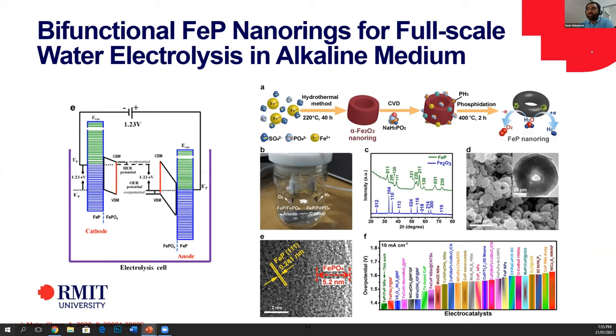So if you look here, we have some surface coating. We have a strain through the ring structure. The ring is hollow inside, so the electrolyte can go easily into the structure. And the strain at the edges or the curve of the ring is very useful to create active sites. When we apply it for the oxygen evolution reaction and hydrogen evolution reaction in alkaline media, it gives us extraordinary performance, and we found that this is among the very best reported in the literature. So that gives us the possibility that we can develop a material which can perform both OER and HER reactions in a single system.